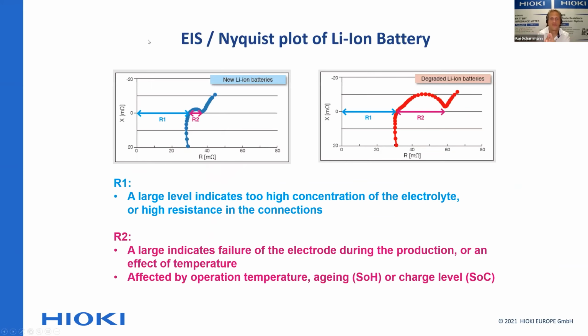The picture a second ago was the principle of this kind of Cole-Cole or Nyquist plot. What you see now is a real-life, proper measurement of a new lithium-ion battery and a degraded lithium-ion battery. You can see that R1 would be the 1 kilohertz measurement that you do. And you can see that the difference between R1 of a degraded lithium-ion cell and a new lithium-ion cell is very, very small. So it's very difficult to make a prediction of the state of health of a battery if you're just looking at 1 kilohertz.